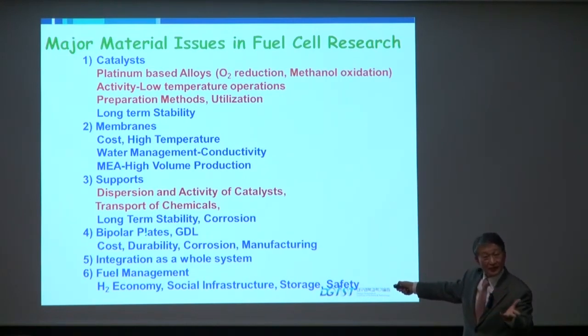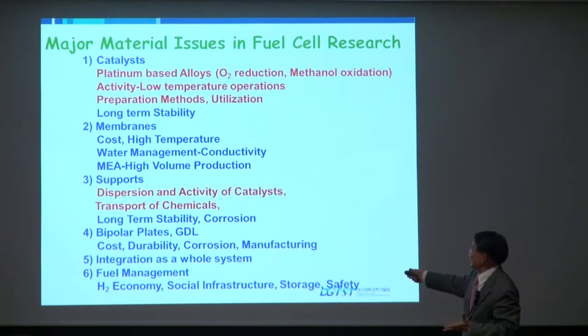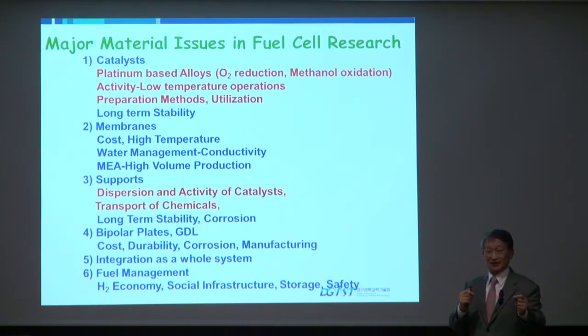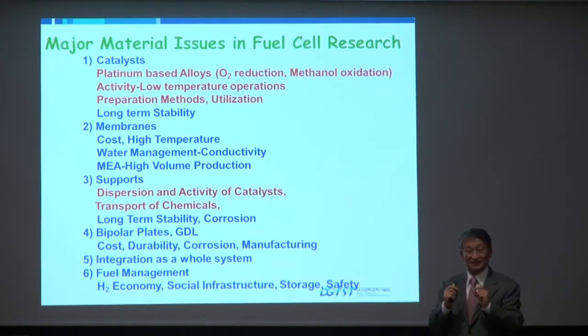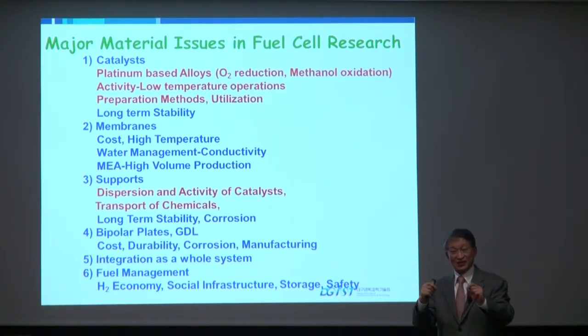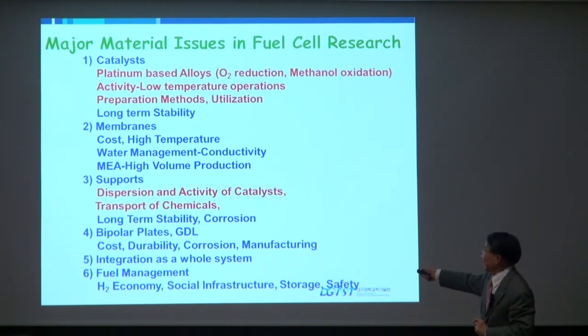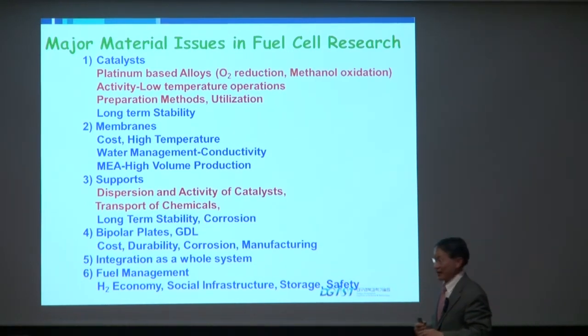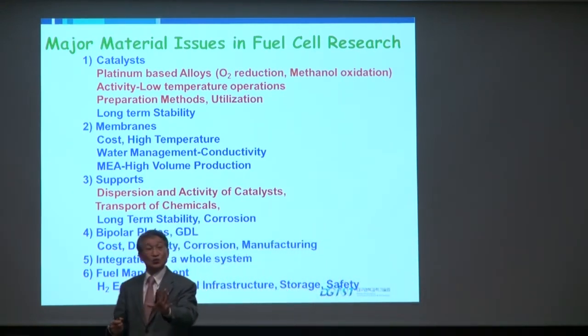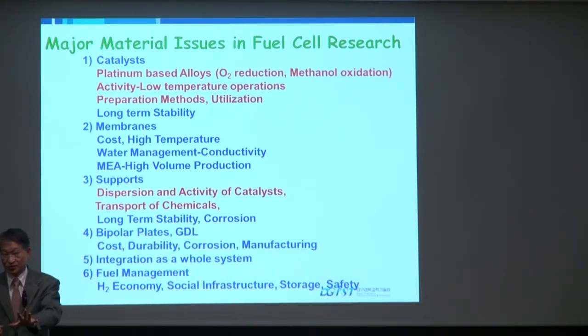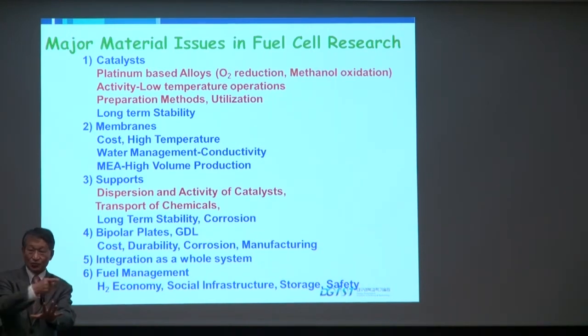Support, I'm talking about carbon. So dispersion of the catalyst, of course, is very important because catalytic reaction occurs at the surface of the support. And also the transport of chemicals. In the beginning, I was mentioning the pore structures of the carbon support, which provides mass transport through this.